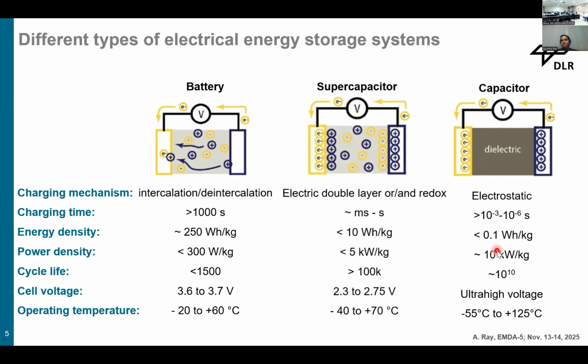After that, there is some research going on the supercapacitor. That is the bridge between the battery and capacitor. It can charge in two processes: the electric double layer process, which is electrostatic, and also the redox reaction, oxidation chemical reactions. It can charge in milliseconds to seconds, quite a bit faster than batteries and almost in the range of a capacitor, not the dielectric capacitor, but it gives higher energy density compared to the capacitor, and higher power density compared to the batteries. So it can give high power density values.